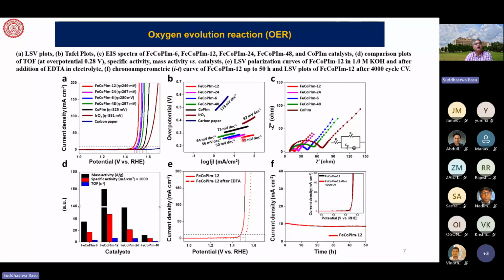you can see that the red line is 43 millivolt per decade, the lowest Tafel slope that you got, so the kinetics is very good for this material, and the activation overpotential, the eta, is about 249 millivolt, right? Iridium oxide is 351 millivolt, much better, close to about 75, or you can say not even 75, 100 millivolt better in terms of the activation overpotential, okay, between iridium oxide bench scale and the iron cobalt phosphonate with 12 hours of reflux.